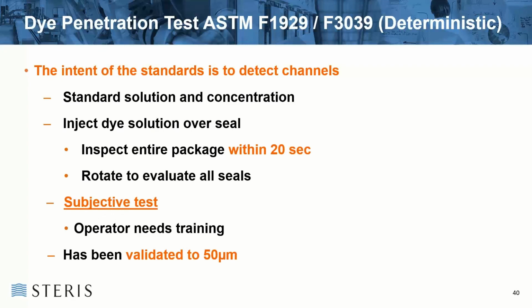dye with the surfactants in it will cause both wicking and leaching of the dye solution out through some packaging, depending on the properties of the packaging. And you can lose sight of a defect that you found very, very quickly.